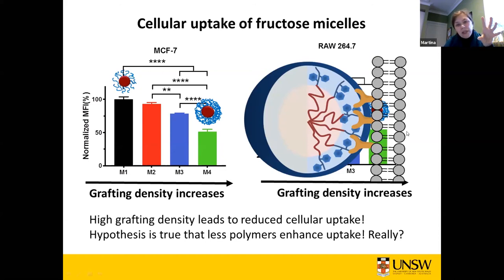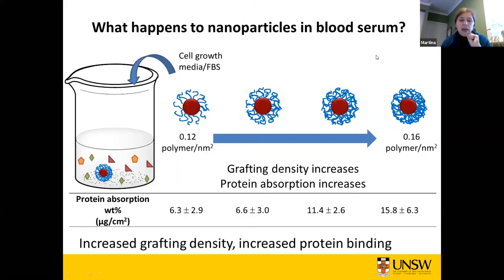However, with things like that, sometimes it's worthwhile to drill a little bit deeper. And we drilled a little bit deeper and said, well, let's actually look at what happens when you put these nanoparticles into blood serum and measure how many proteins are absorbed non-specifically. And what we found was that actually this very thin, dense layer here absorbs the highest amount of protein. So what we really had here was not a sugar-based nanoparticle. We had a lot of proteins around here that might have inhibited the specific interaction with the cell.